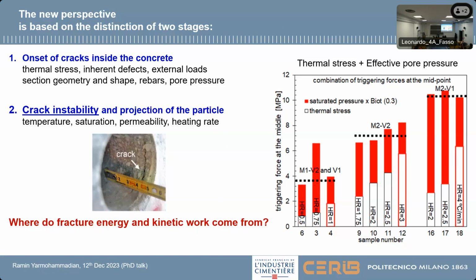But as you see, the combination of both of them gives a constant value for each concrete. So it is kind of a material property, the threshold. But if we have different boundary conditions, the share of these two contributions is different. With higher heating rates, we're going to have a higher share of thermal stress.